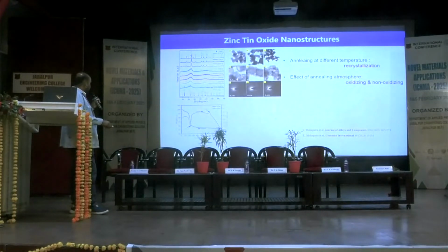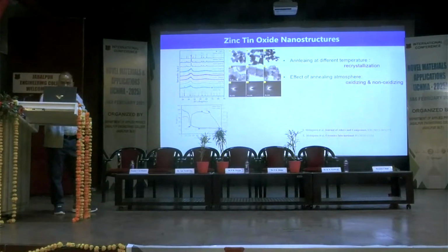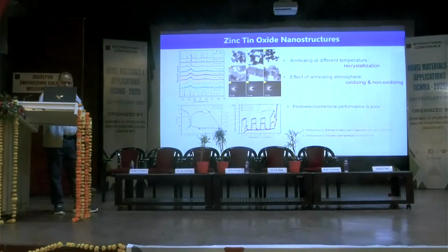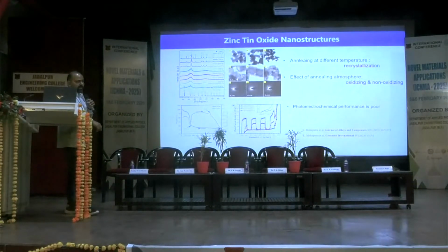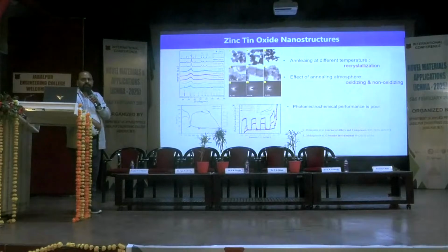Then we heat treated the same sample in other environments, oxidizing and non-oxidizing. We took different gases, and we heat treated even in the presence of ammonia, which is a reducing environment, and also in a non-reducing environment like oxygen. Again, we made the electrode and tested the electrochemical performance. But as I said, these are in powder form, so they do not have very good electrical conductivity. Also, the response is not so fast.